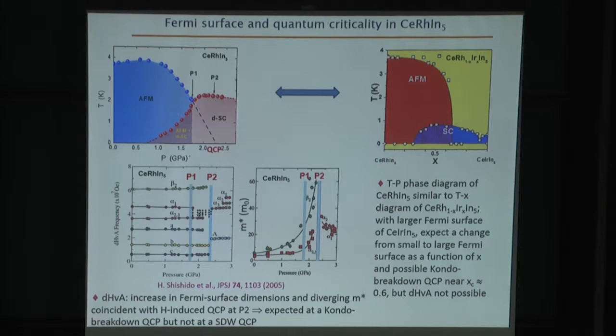So this would suggest then that there should be a change from a small Fermi surface, a small Fermi volume in cerium rhodium indium-5 to a large Fermi volume somewhere as a function of iridium substitution, and furthermore we know that there's a magnetic boundary in this phase diagram as well. So this suggests that perhaps somewhere as a function of iridium substitution for rhodium, presumably near this boundary here, one might expect to find evidence for a so-called Kondo breakdown quantum phase transition. But unfortunately, because of strong disorder scattering in this substitution series, it's not possible to make these kinds of de Haas van Alphen measurements. So we have to use a different approach.